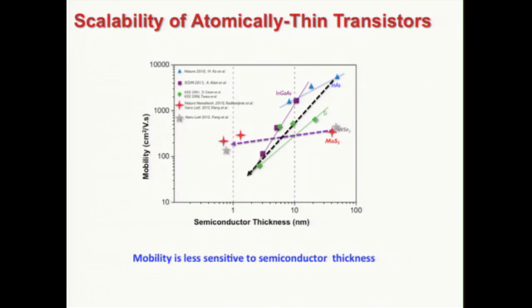But in typical 2D materials, like molybdenum disulfide, in general layered semiconductors, we already have very low mobility, maybe just a few hundred square centimeter per volt second, but this is much less sensitive to body thickness. So we still have some variation, but it is almost preserved. In a high quality monolayer or few layers of tungsten selenide or molybdenum disulfide, we can measure mobility up to 100 or 200 square centimeter per volt second, which is way above what we can measure in conventional semiconductors with the same thickness.